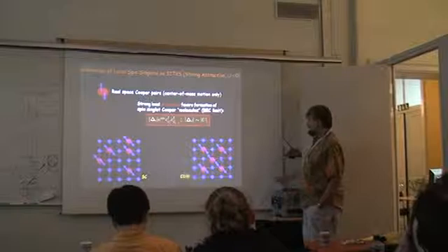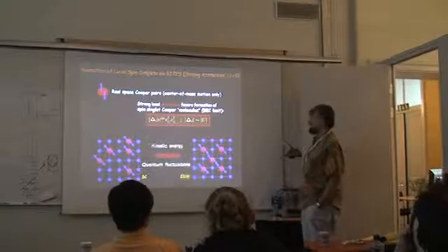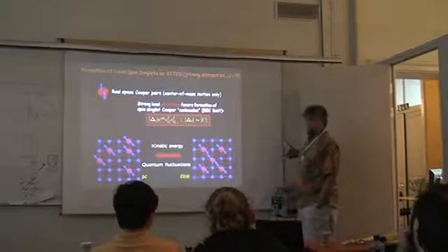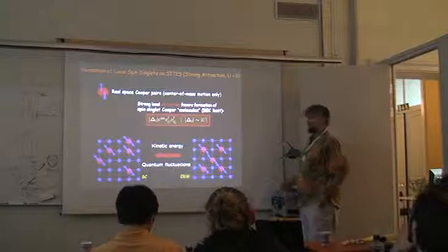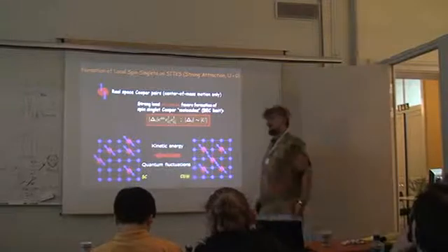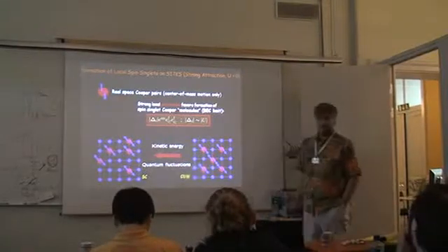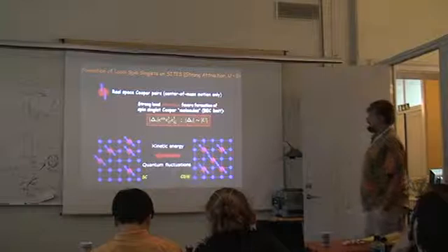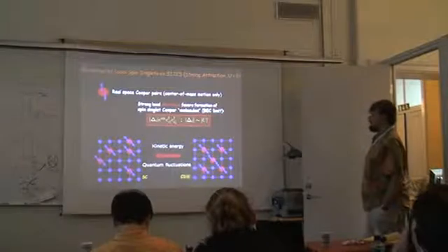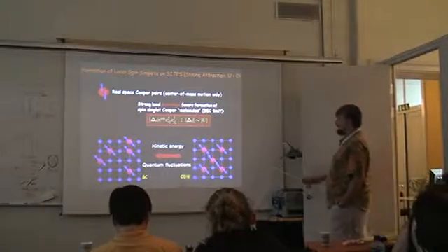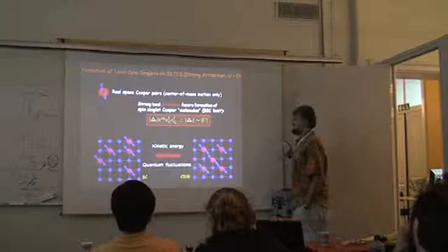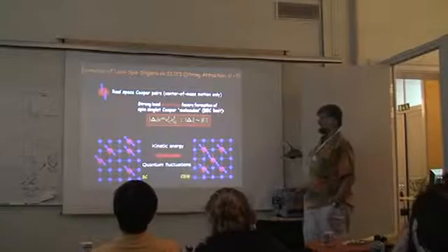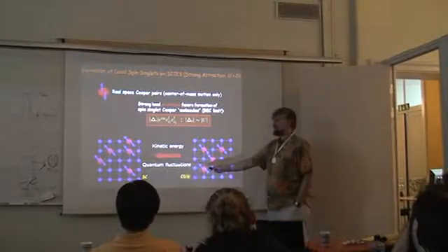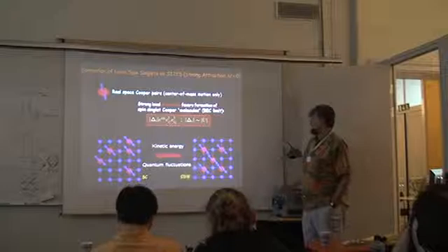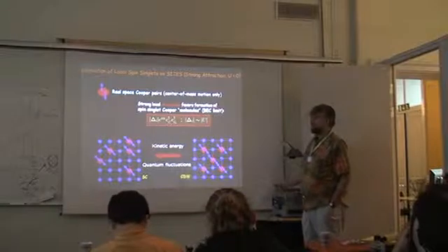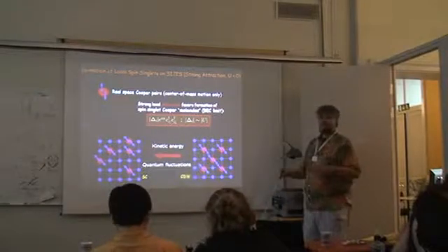And the way they lock in is, once their kinetic energy is low, residual Coulomb interactions basically lock them in into some particularly preferred magic fillings depending on the underlying lattice. And so, if kinetic energy is large, we will in general have the superconducting state. If kinetic energy is weak, we will have this. And so this can be understood in various ways.